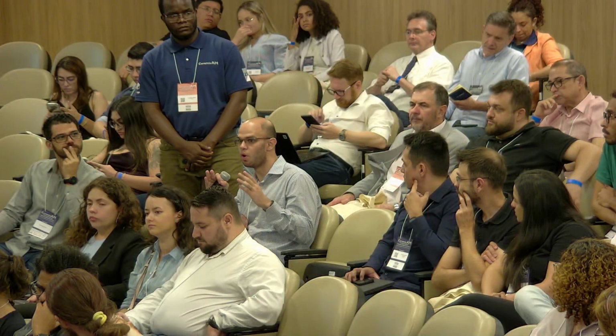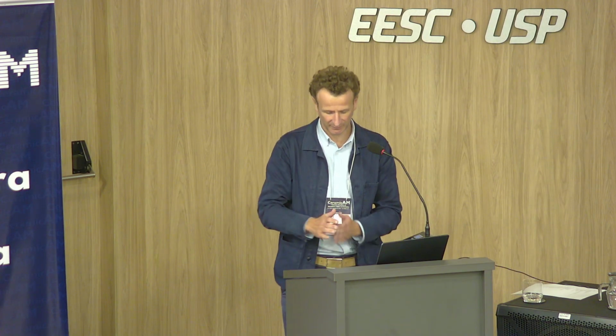Thank you for your very nice presentation. Concerning debinding, you said it could take several days, but what's the maximum wall size that you can get? Today in alumina, our recommendation for customers is a maximum of 6 millimeters sintered. But in collaboration with INSA in Lyon, we developed 10 millimeters, with more days in debinding. After sintering? After sintering, 10 millimeters. Great, thank you.